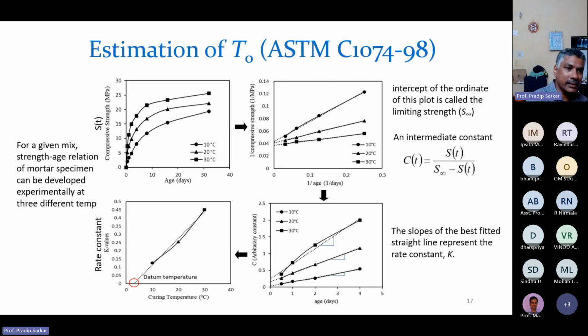So I will prepare the same mix in the laboratory, and the strength-age relation of mortar specimens can be developed experimentally at three different temperatures. So these are the three different atmospheric temperatures. We create the compressive strength versus age plot of this, and we get different slopes, and this is 1 by the slope, and this plot numerically we can make, and we get the values, the y-intercept.